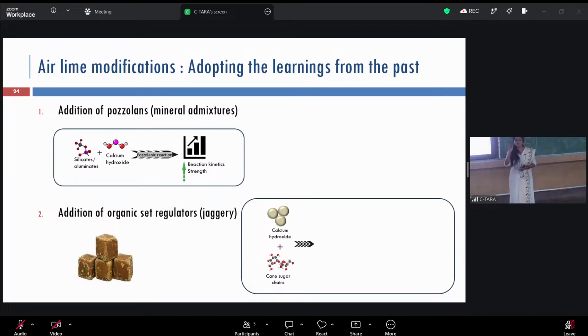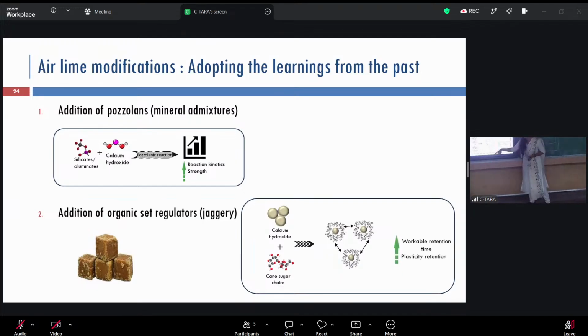If you're having jaggery, the jaggery molecules will go and adhere and get attached on a calcium hydroxide molecule like this. So the external surface is not immediately carbonated. When CO2 comes in, it has space to go into the surface and it starts carbonating from interior to outside. So you're getting a better carbonation, quicker carbonation, and proper carbonation when you're using jaggery in lime system.